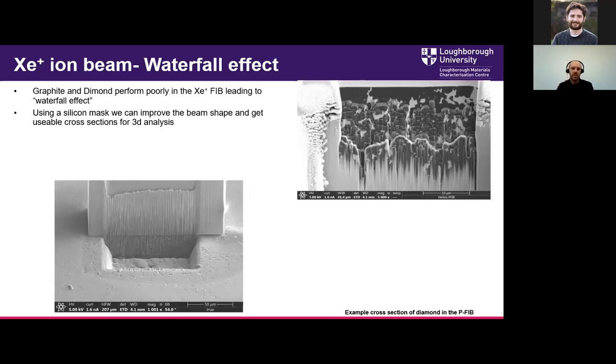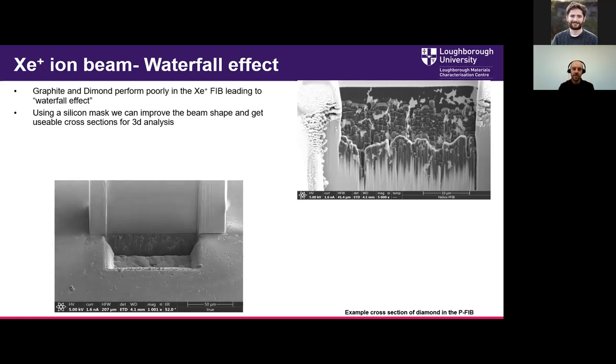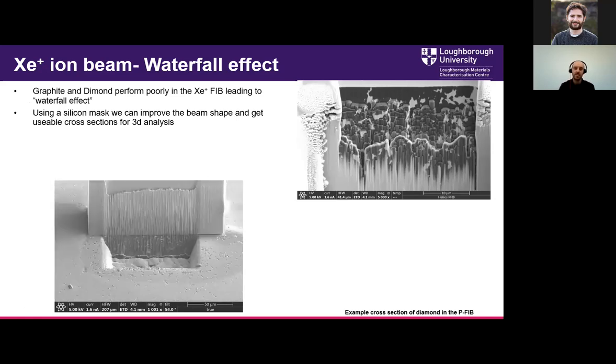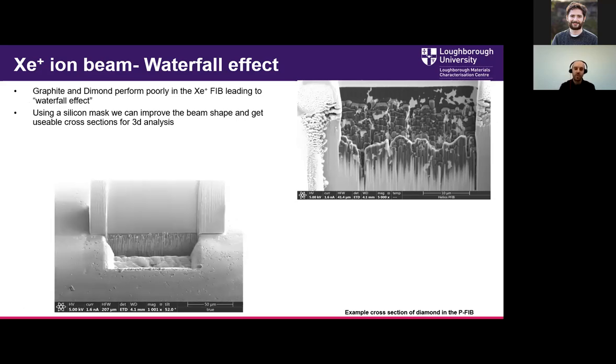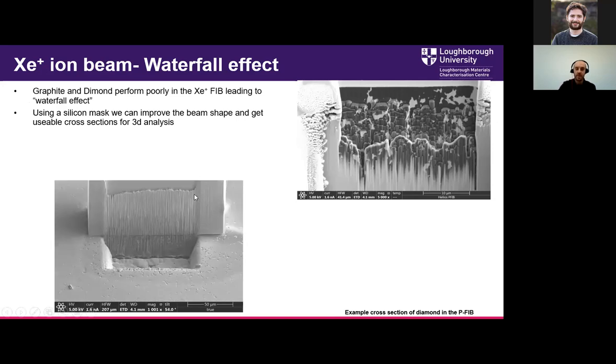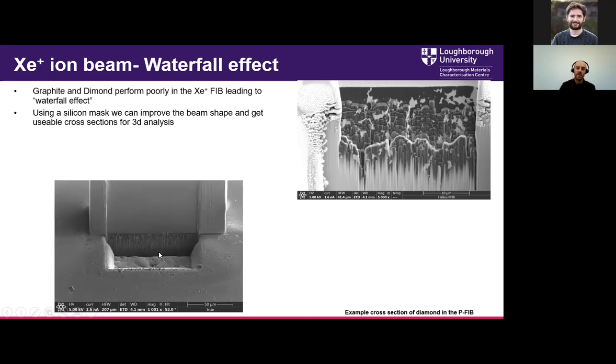Another thing we've been working on to try and overcome this waterfall effect in materials like diamond has been using silicon hard masks. This is a trick really stolen from broad beam ion milling, where you place a large chunk of silicon on top of the surface of your sample, and this tidies up the shape of the ion beam and allows you to cut a much cleaner cross section.